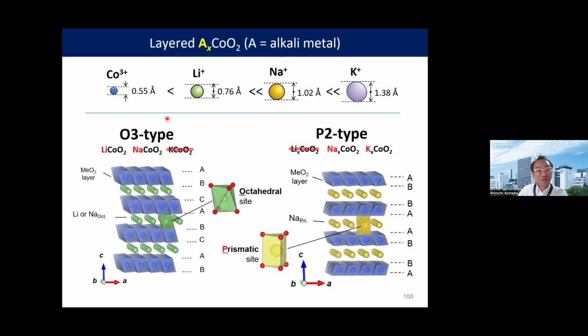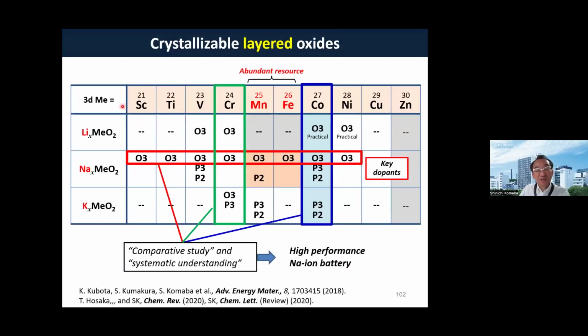Anyway, now sodium-ion is very attractive for layered oxide, because with the larger size than lithium, for sodium we have not only O3 type layered oxide, the same as lithium, but also P2 type, which is not possible for the lithium case. So in the case of sodium, we have both O3 and P2 types, different polytypes. Then we can have a very wide variety of crystal structures and also a wide variety of transition metals to crystallize the sodium layered oxide. From scandium to nickel, we have the O3 type structure, and P-type stacking is always observed for sodium and potassium, but never observed for lithium.